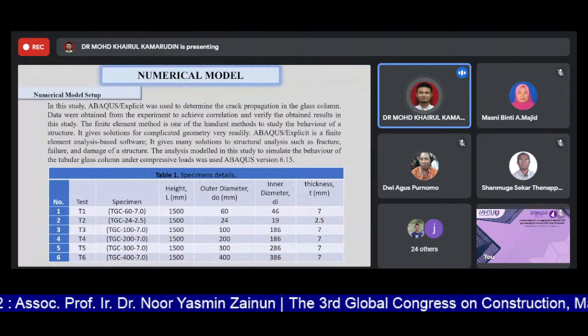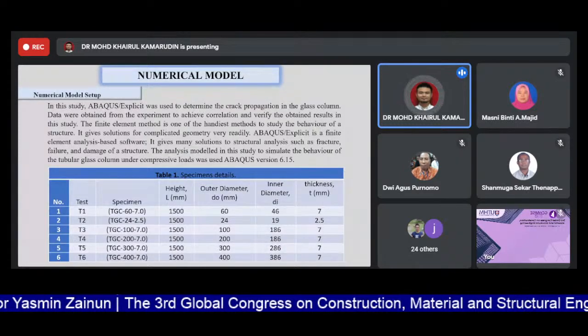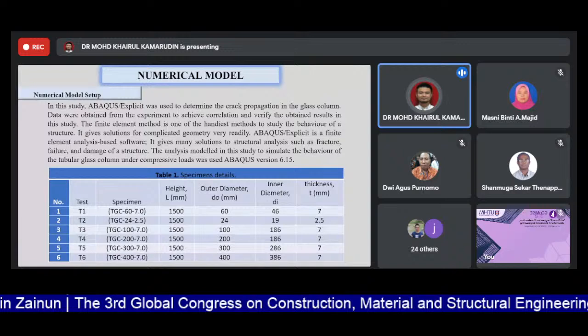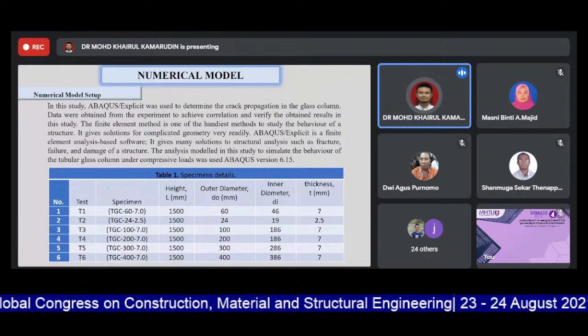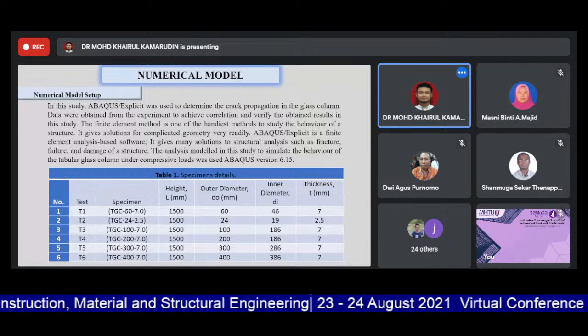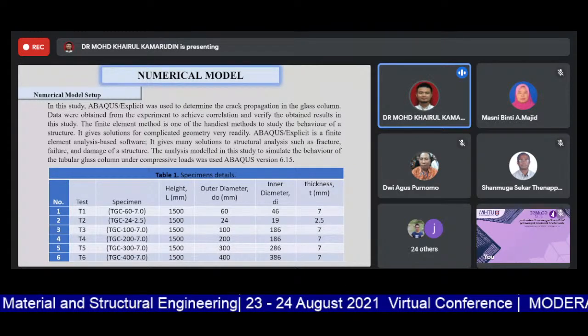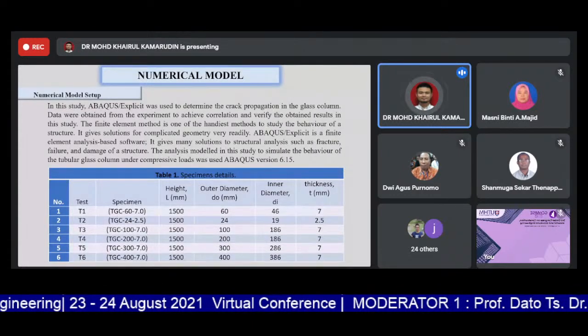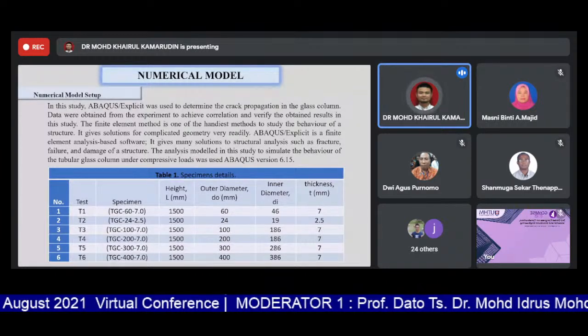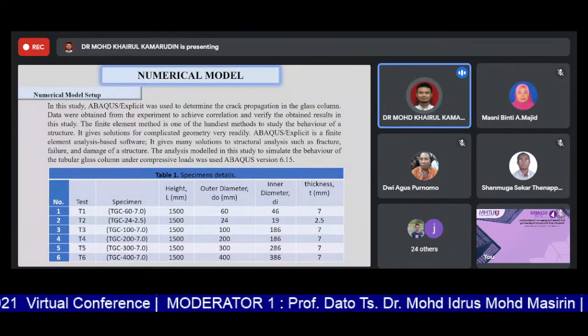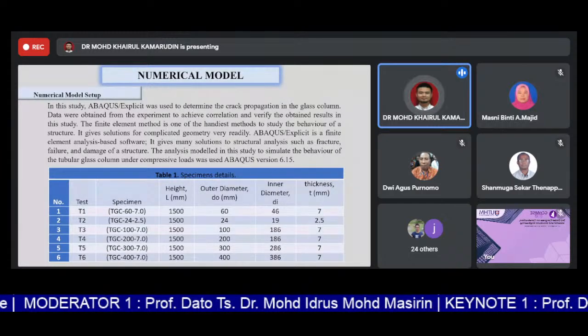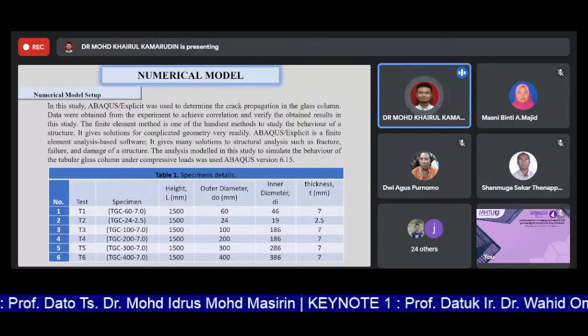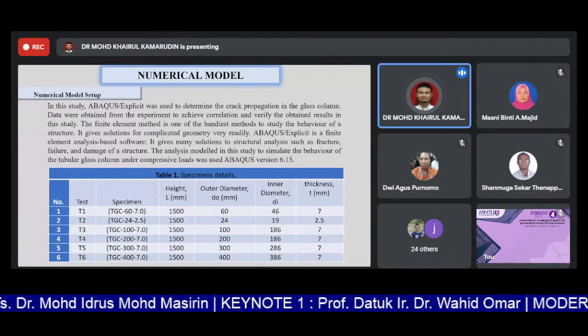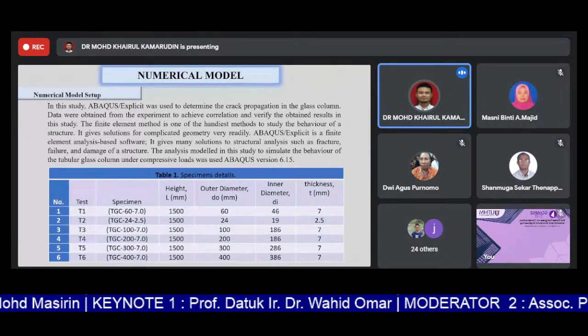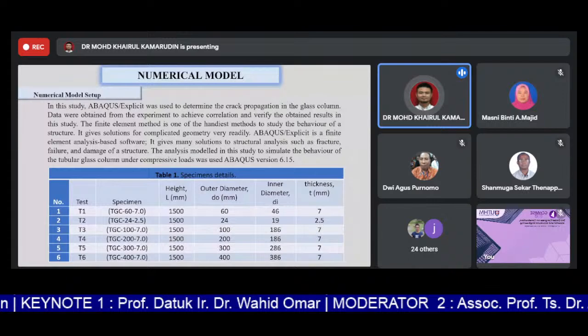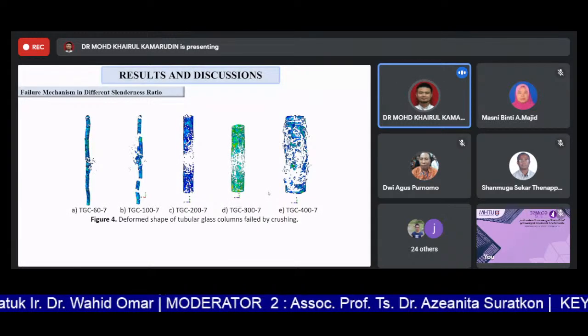Technically the most important configuration that needs to be included in the analysis is to ensure that we have the parameters, the crack after the collapse happened and so on. So those parameters are very important to conduct this brittle cracking model in Abaqus. So basically, we have 6 different dimensions with the same height, with different outer diameter and inner diameter, and also the wall thickness of the glass tube.